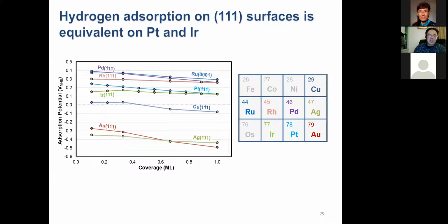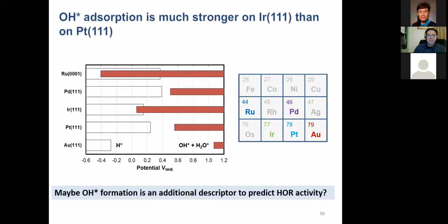There must be something else that dictates the rate of the hydrogen evolution reaction or the hydrogen oxidation reaction, both of them being faster on iridium 111. What is quite different between platinum and iridium is how strongly they bind hydroxide. On platinum 111, I showed you hydroxide did not bind very strongly, and that was a separable high potential peak. But on iridium, down there in that hydrogen evolution reaction range, hydroxide will be on the surface.